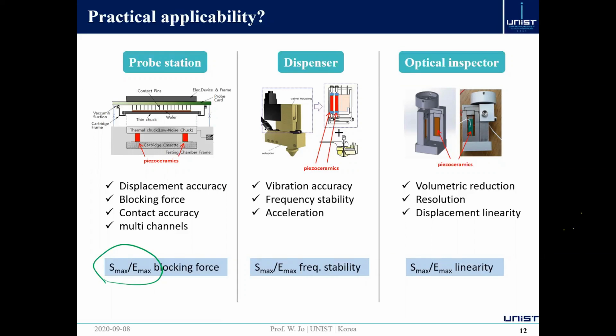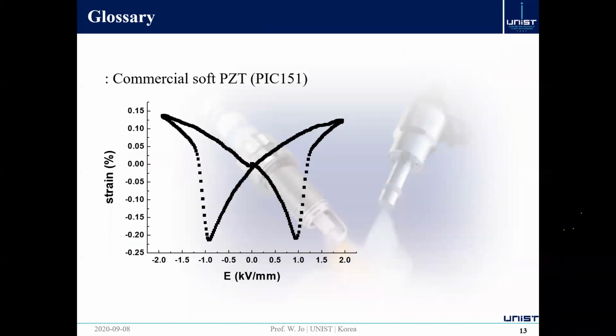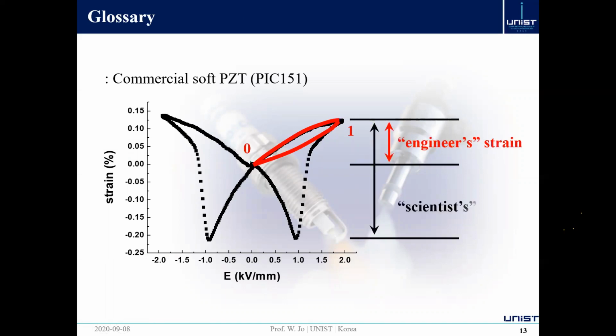But when it comes to ferroelectric-based piezoceramics, the problem is we have ferroelectric domains in there. That gives you hysteresis. That's why domain contribution usually deviates D33 from Smax/Emax. The example is like this. This is from a commercial PZT. This is the bipolar strain behavior. And as you already know, I usually call this red line the engineering strain, because a real-time application only requires a unipolar strain.